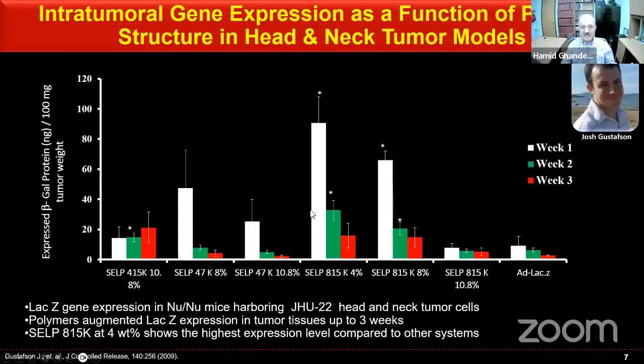The bottom line is that everything else being equal, not only polymer concentration, but importantly, the structure of the polymer has a profound influence on how much of these adenoviruses are released and provide gene expression over a period of time. The reason that you see this decreased expression doesn't really have to do anything with the polymer. Rather, it has to do with the fact that the viruses lose viability over a period of time.